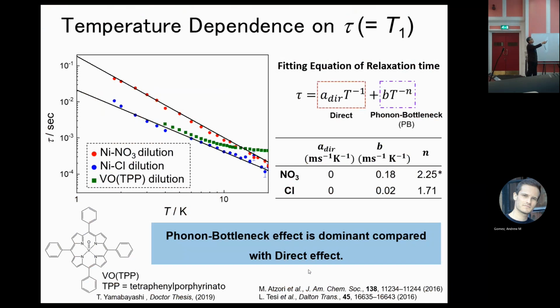Ni-NO3 is longer, NiC chloride is shorter because chloride has a nuclear spin. So the nuclear spin disturbs the coherence, then NiC chloride has a shorter lifetime. But in NO3, oxygen coordinates to Ni, and oxygen has no nuclear spin, then longer lifetime. So Ni-NO3 has the longer lifetime.